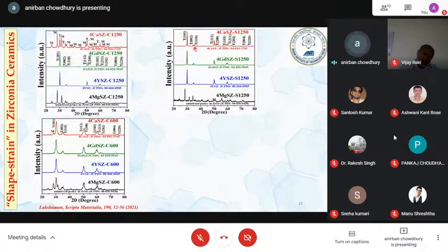Okay, fine. Then you see the same, just calcined at 1250. This is sintered at 1250. It's calcined at 1250. When you calcine at 1250, you see the biggest change. The Mg remains similar. Y remains, yttria, Y2O3 remains the same. Gadolinium remains the same. The big change is in calcia. In calcia, you see that there is a full monoclinic phase appearing, and here there was nothing.